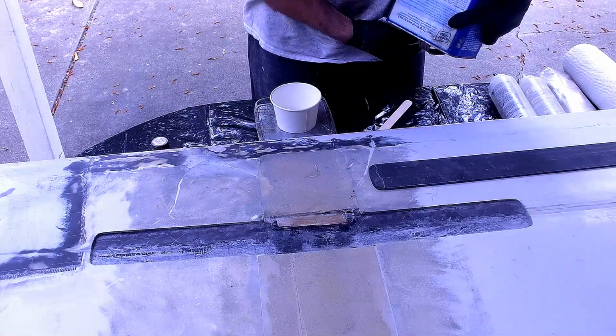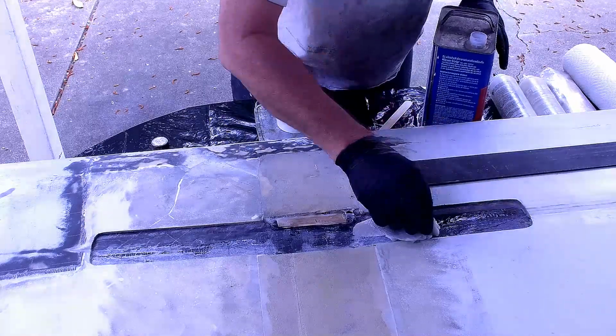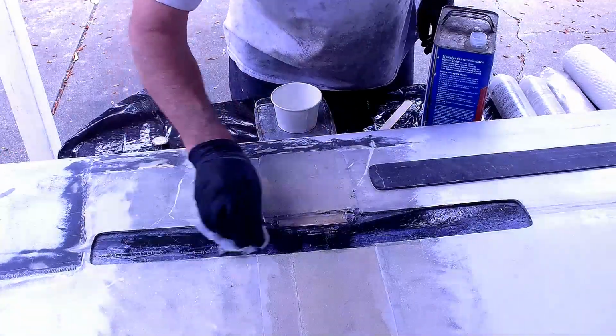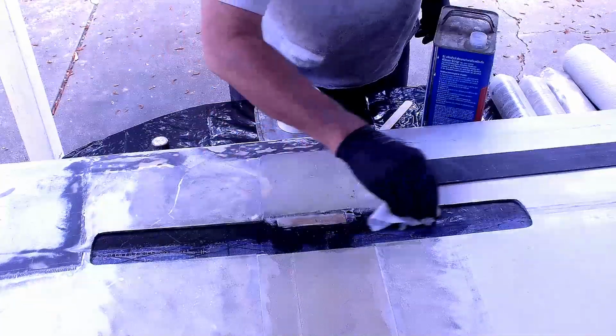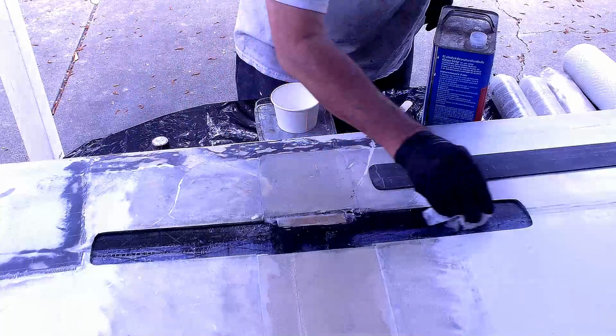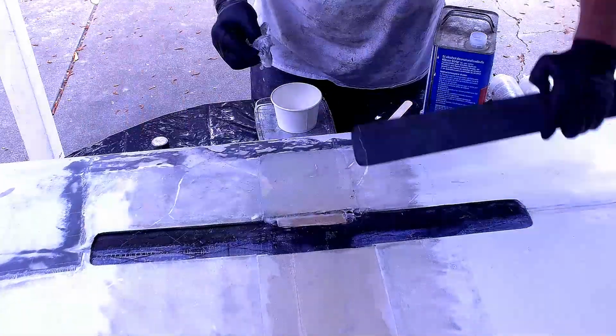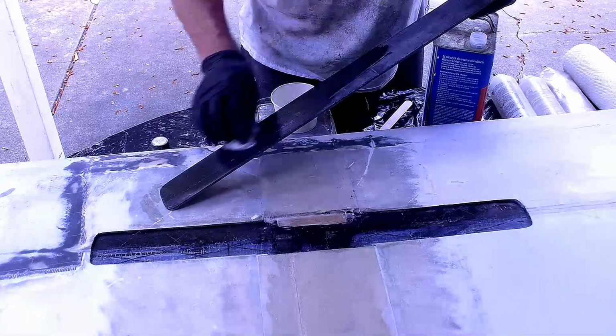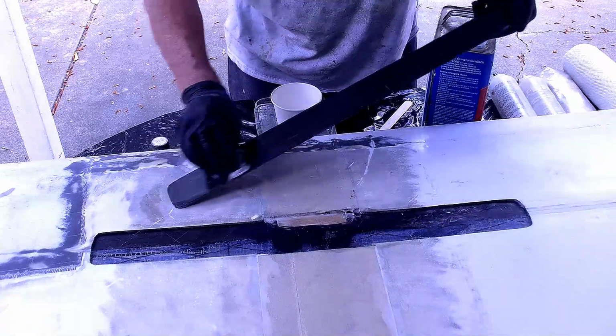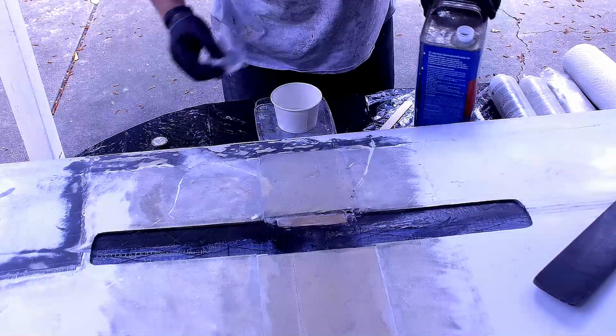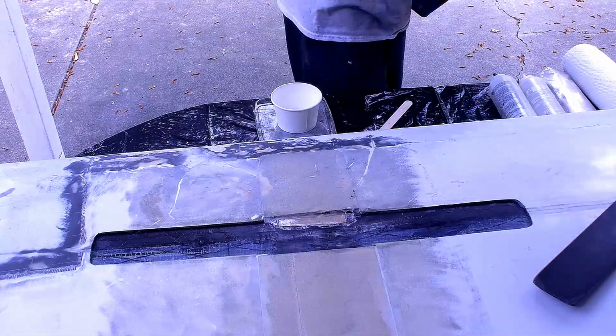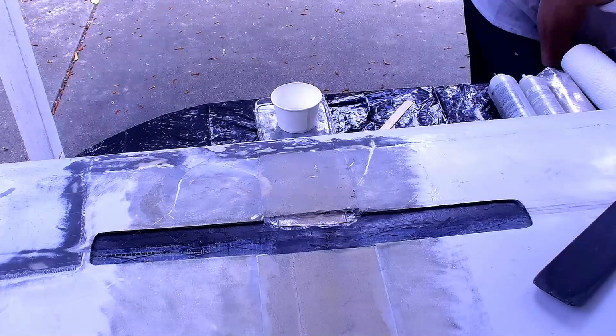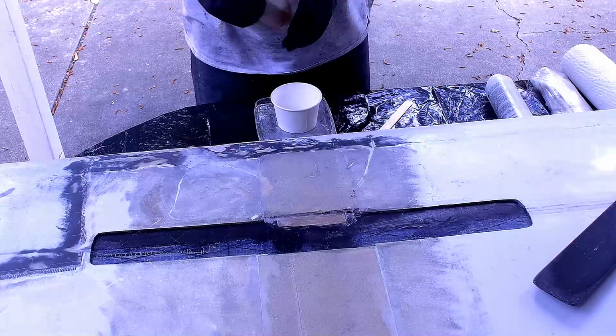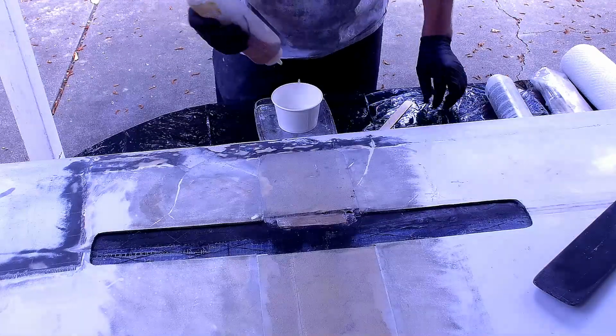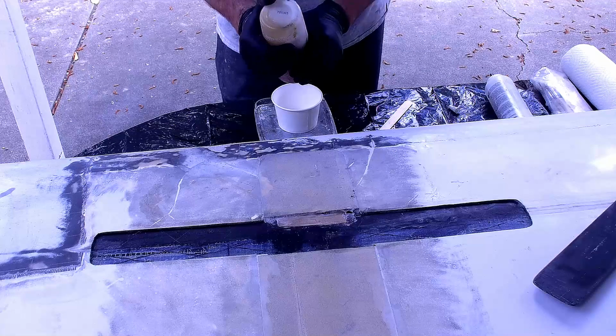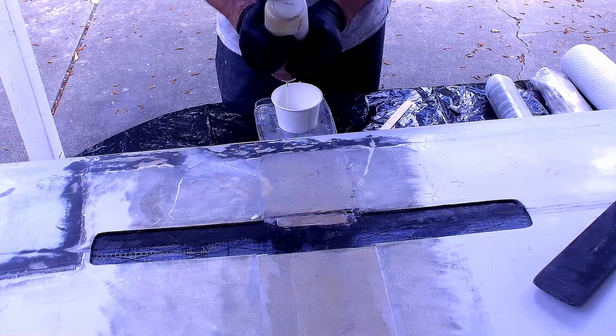Okay, in this next segment, you're watching me perform the repair of the lower main spar. What you see me doing here is cleaning the surface first with alcohol. Make sure we take all the oil and finger grease and so forth off. I have used a router to remove the wing skin. The wing skin is about 1/8 of an inch thick, and what you see me cleaning here is the spar repair piece. That is a series of 6 pieces of pultruded carbon fiber that is 1/8 of an inch thick, and I've bonded those 6 pieces together with 3-ounce fiberglass on top and bottom, and it was molded on the same mold that I used for the D-tube so that it will match the shape of the spar.